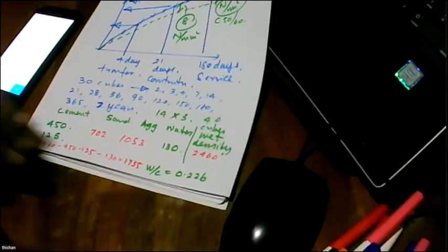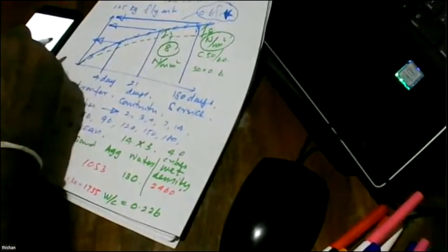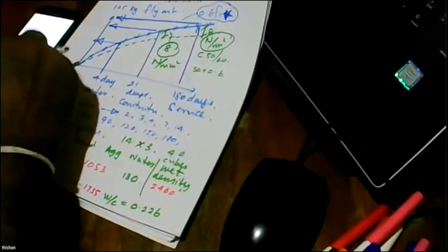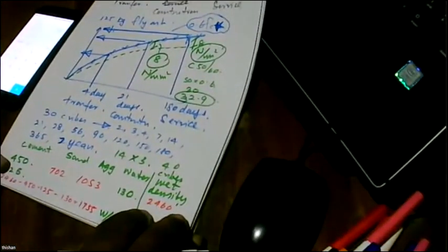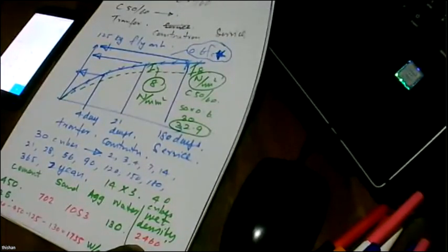But now you can see we are going for C40, C50, 60 concrete. So 50 multiplied by 0.6 is what we are targeting, and that is 30, and then again another 2.9. So you get about 32.9 megapascal stress range. A huge stress range, but cost-wise, you are still at a lower level. But how we achieve this is by going for trial mixes.